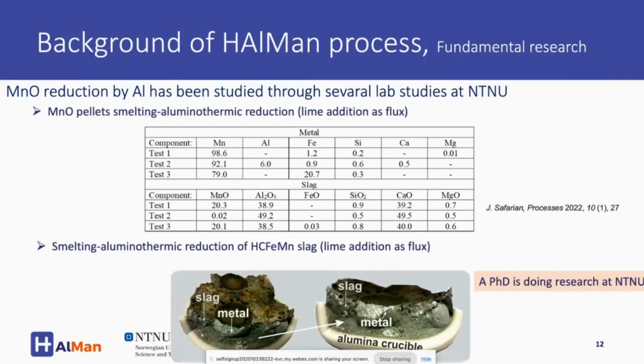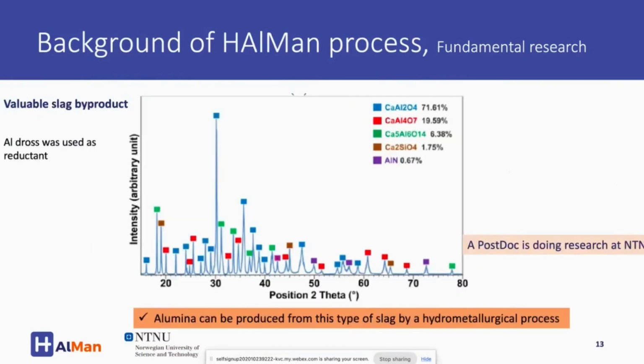At the moment, there is a PhD working on the aluminothermic reduction of reduced manganese ores at NTNU. Next slide, please. The main byproduct of the HAlMan process is calcium aluminate slag, and you see here a typical XRD of calcium aluminate slag, and we have several calcium aluminate species in the slag. This slag can be processed hydrometallurgically, and we extract alumina for the aluminum industry, or smelter grade alumina. Currently, a postdoc is doing research in this area as well at NTNU. Next slide, please.